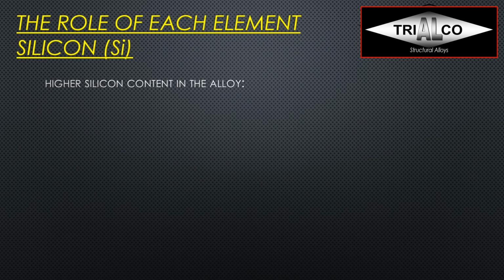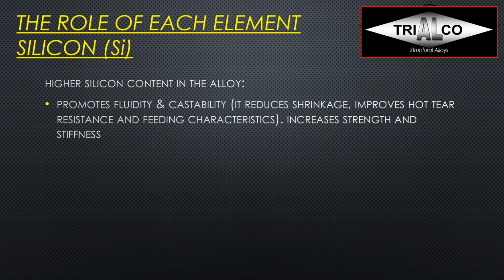So now let's have a look at the role of each element. And let's of course start with silicon, as it's the biggest alloying element in all foundry alloys. Higher silicon content in the alloy means it promotes fluidity and castability, it reduces shrinkage, it improves hot tear resistance and feeding characteristics. It also increases strength and stiffness even on its own.